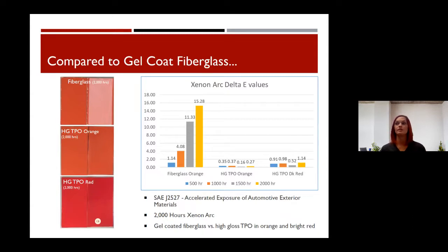Just a quick slide compared to a gel coat fiberglass. We looked at it in an orange color as well as a dark red. Typically, we use the automotive standards, indoor and outdoor SAE for accelerated weathering. Rule of thumb's about 1,000 hours is 1 year of South Florida exposure. And we looked at the fiberglass against the high gloss TPOs, and you can see the fiberglass is good to a point. About 1,000 hours, you get a 4 delta E. In that bright of an orange, you're going to start to be able to visually see differences around 3 delta E. So it's good for about a year, but after that, it dramatically starts to fail.